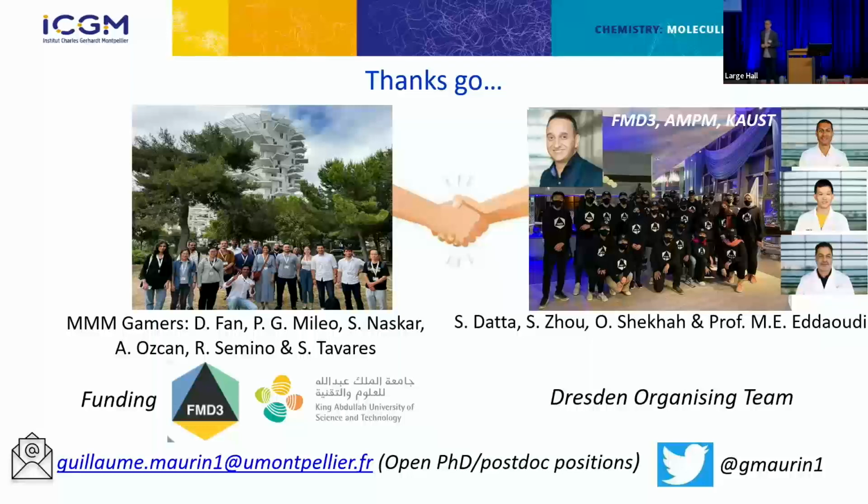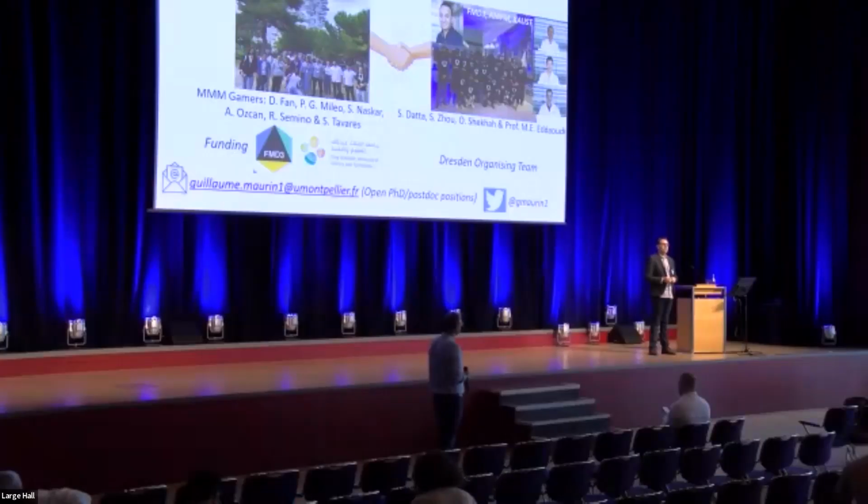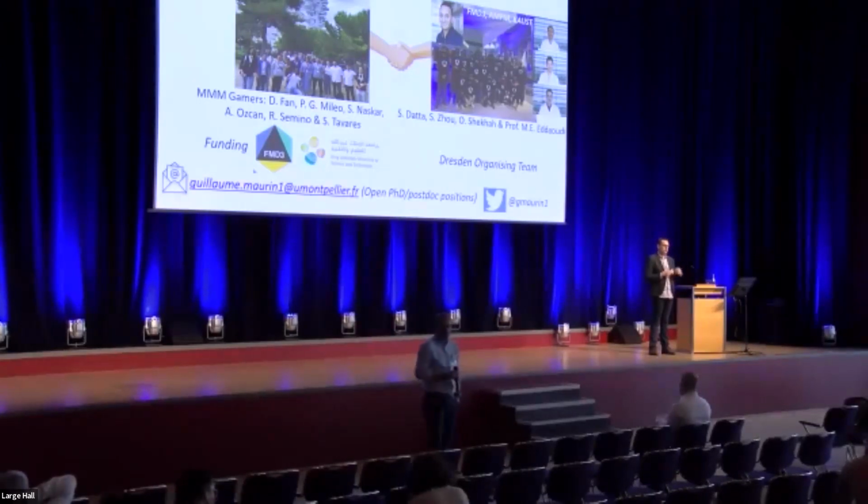Okay. I want to have a question after you. I'm quite interested in the PIM simulation. What kind of simulation method do you use, DFT or just dynamics? You mean for the construction of the PIM1 model? Yeah, PIM1. In that case, it's just force field calculation, where you make an in silico polymerization, but you just rely on the charges that you can extract by DFT. But everything related to the construction of the polymer model is based on force field calculation.